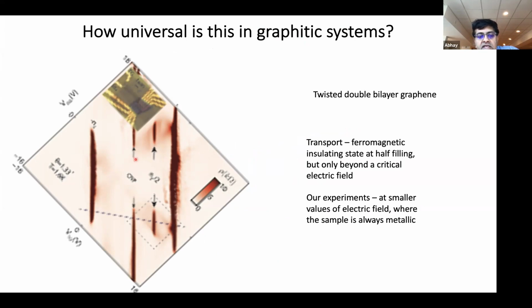Once again, this is the transport phenomenology of this particular system. At charge neutrality, and in the absence of an external electric field, the material is a semi-metal, it's conducting. At exactly 1/2 filling, once you start to apply some electric field, you can drive it into an insulating state. So this is a material which has a slightly richer phenomenology than twisted bilayer graphene. You need that electric field to drive it into the insulating state. And as Peng-Cheng asked, this insulating state appears to be ferromagnetic in transport.